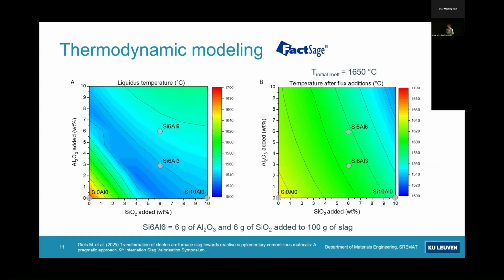So we used FactSage then to do some modeling. Basically, we added silica and alumina to decrease the liquidus temperature, and we checked what the effect on this liquidus temperature was. So we saw silica and or alumina addition reduced liquidus temperature. Not so new yet. We did that also to see if the melt is freezing. If you add these additions, and actually after 2%, I think, more or less, all the additions you do lower the liquidus temperature much more than the melt temperature itself. So in theory, the melt should not freeze when you add these additions.